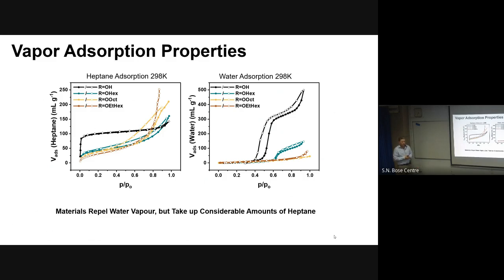One thing that was of interest to us was that the side chains are very hydrophobic, so they are very non-polar. We wanted to look at water adsorption and adsorption of hydrophobic molecules. Interestingly, water is adsorbed only very well in the non-functionalized material, where we only have some hydroxy groups. The materials with the octyl chain and the branched side chain don't take up any water, so they are hydrophobic too. The heptane adsorption then looks a bit different. The hydroxy functionalized material takes up quite a lot of heptane.